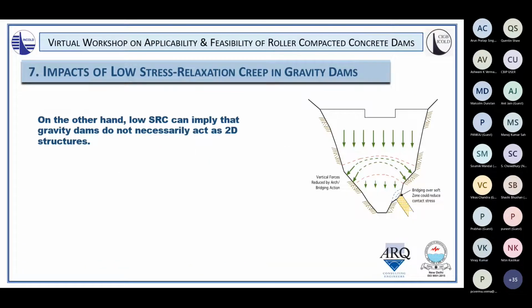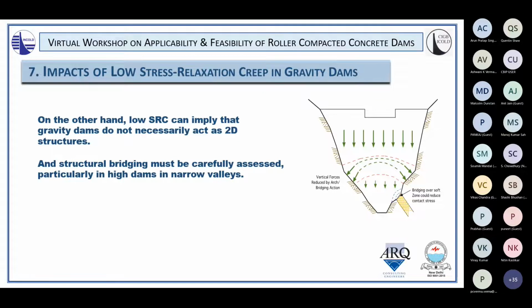Now moving on to what this means for gravity dams. So great opportunities in terms of arch dams, but negative effects in terms of gravity dams, because low stress relaxation creep can imply that gravity dams do not necessarily act as two-dimensional structures. Structural bridging must be carefully assessed, particularly in high dams in narrow valleys, or where zones of weak material are present in the foundation, because literally we create a bridge across those zones and potentially don't have a contact pressure between the dam and that foundation in these places.